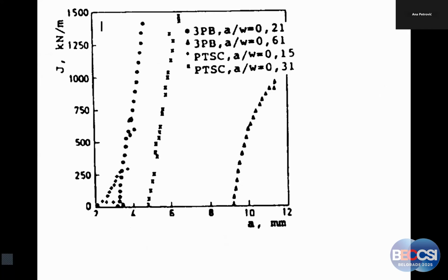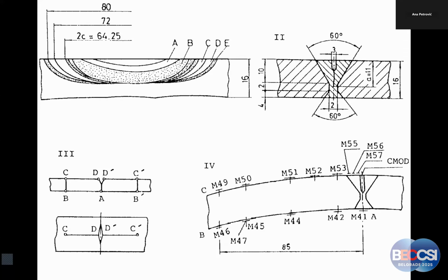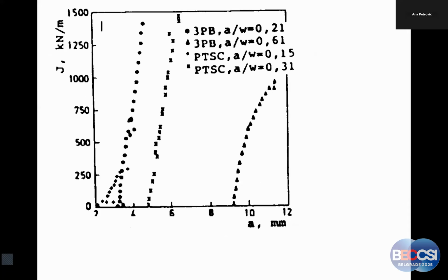These M's are actually strain gauges, and there is a CMOD gauge, a measurement device, here, and that's all we need. So just memorize that all we need are strains along the outer path plus a CMOD measurement device to measure it, and strain gauges along the other outer part. Knowing all that, we can get J integral by direct measurement because we can use those simplified expressions that I showed. And then it is